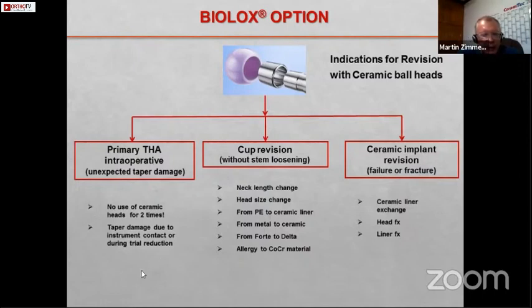You can imagine that during a primary hip surgery, for any reason, you can have a taper damage occurring with an instrument. And if you have a damage on the surface of the taper, you create locally a kind of scratch. And this is strongly recommended to not use a ceramic ball head, because we know that locally you have an increase of the stress, which can strongly increase, let's say, the risk of fracture of the ceramic ball head. So this is always recommended to have it in case something like this occurs during the surgery.